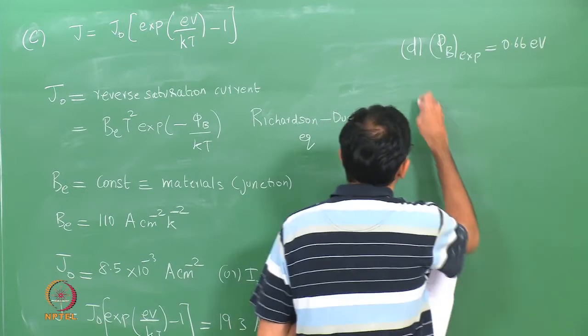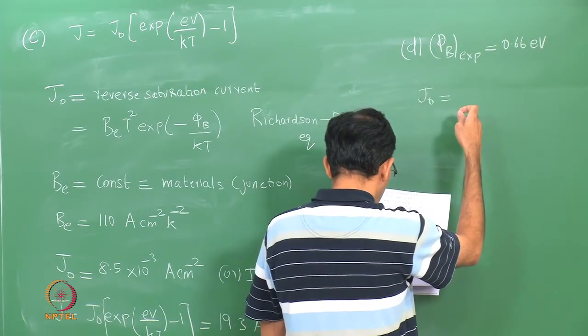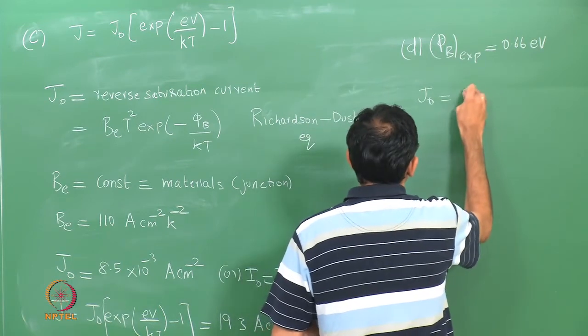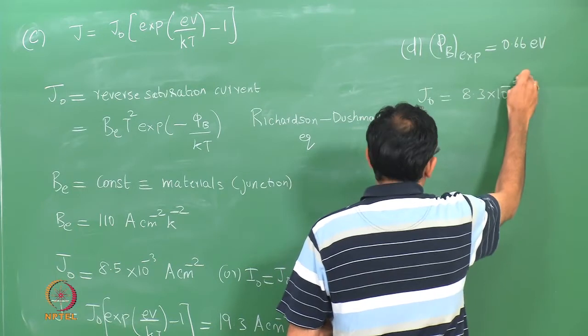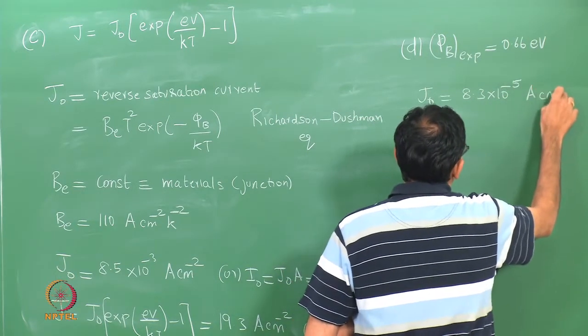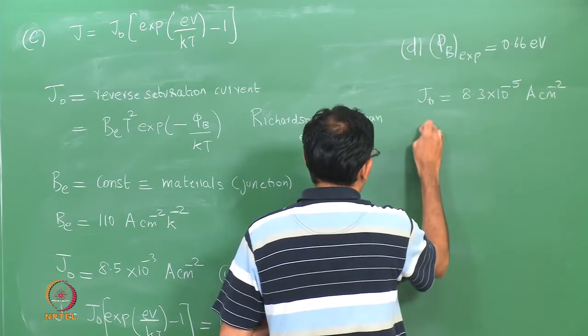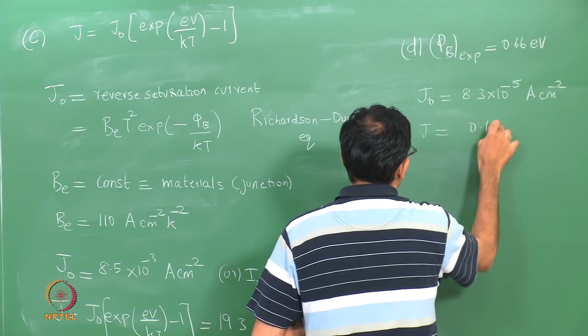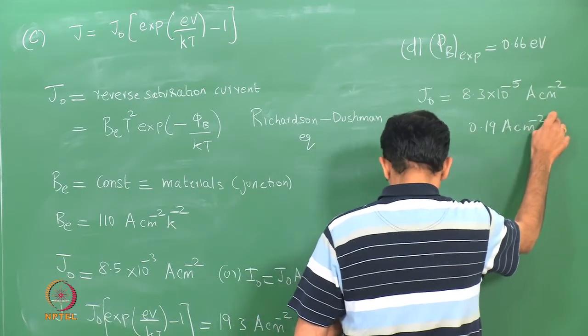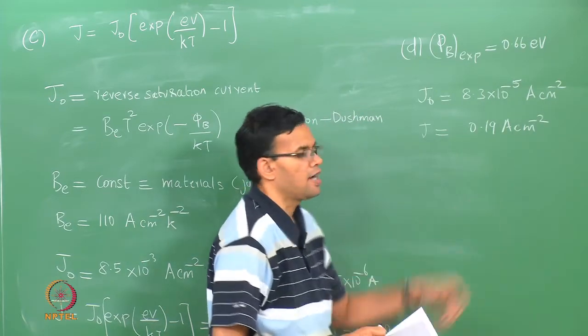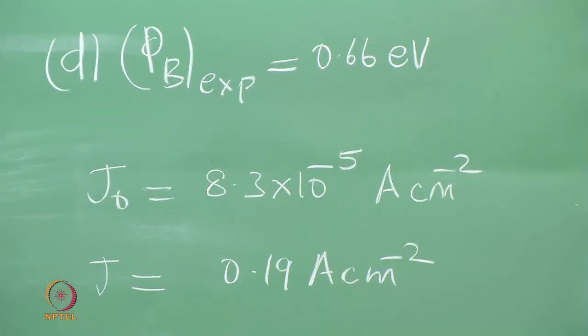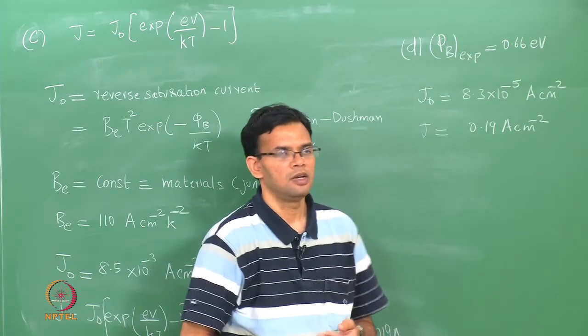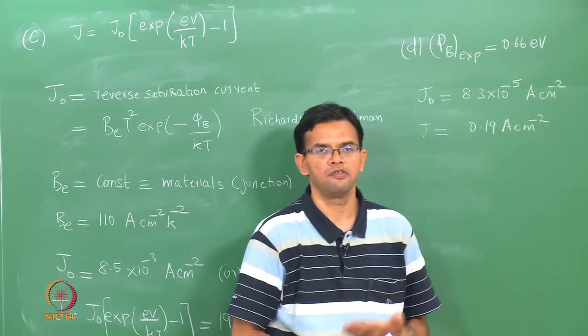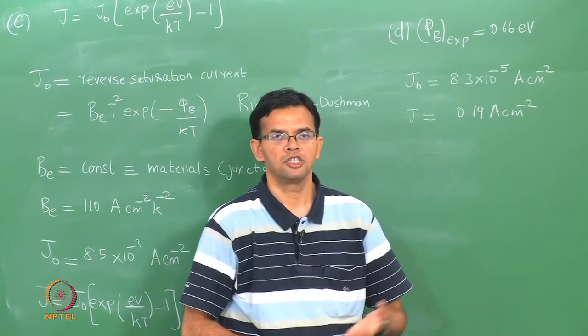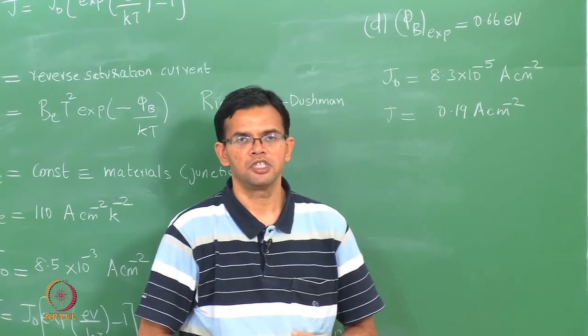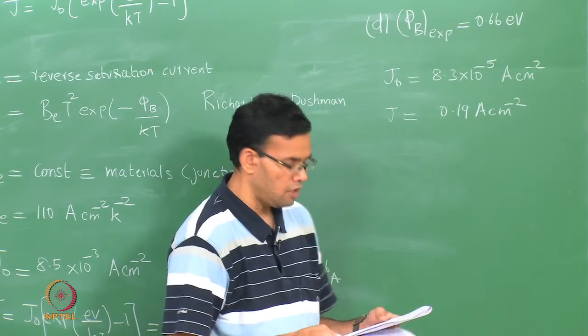So, in this particular case, J naught comes out to be 8.3 times 10 to the minus 5 ampere per centimeter square, and current J is 0.19 ampere per centimeter square. So, the actual current is slightly lower than what we would expect if you use the theoretical values, but the important fact is that it is still 3 orders of magnitude higher than J naught, so that your Schottky diode or your Schottky junction still functions as a rectifier. So, let us now go to the next problem.